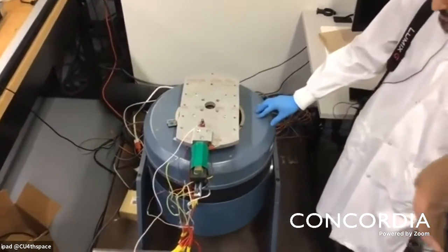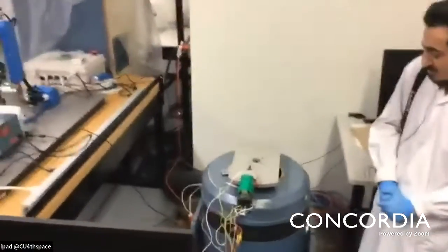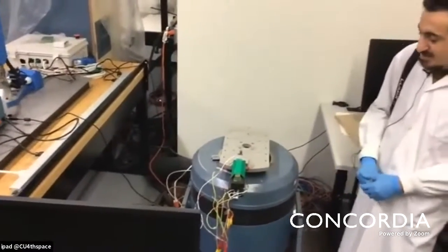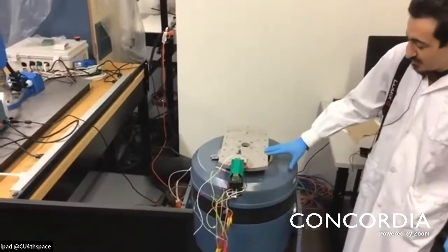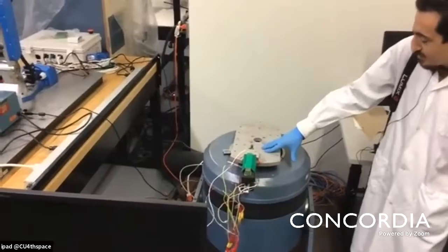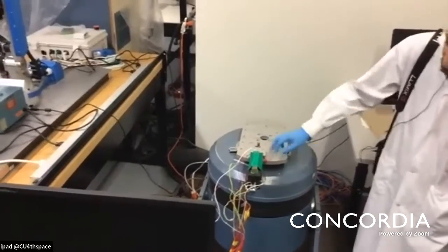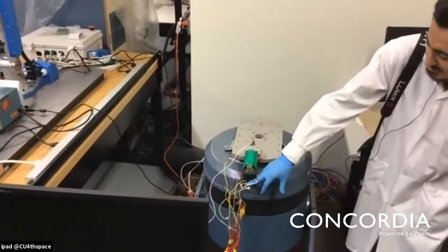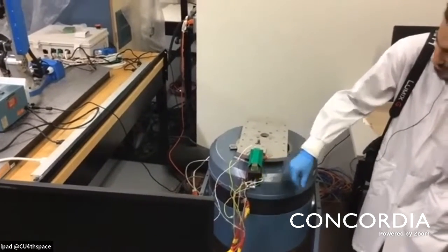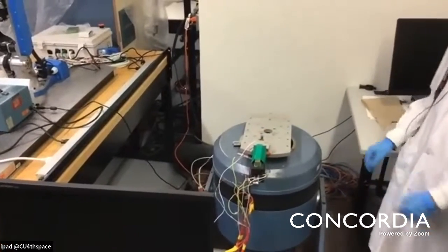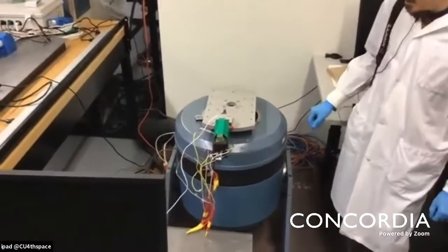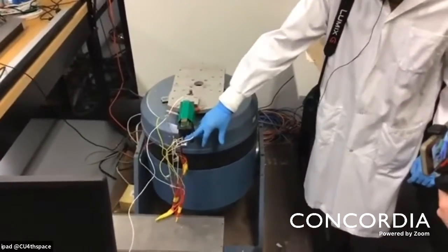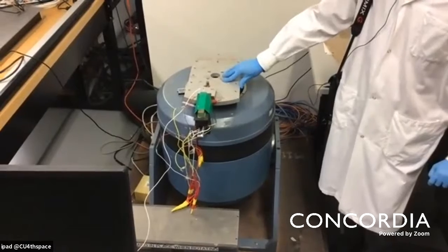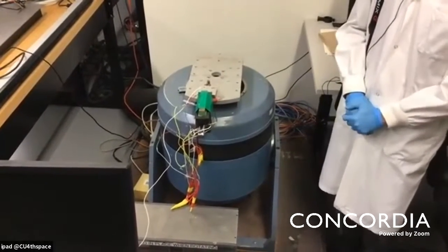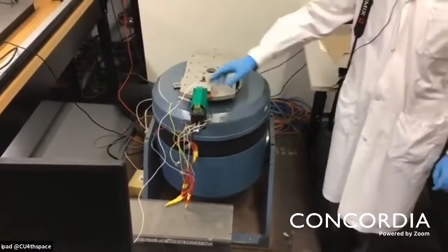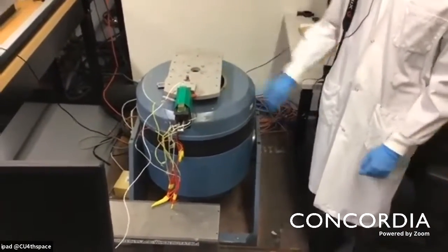So by using this device, we can create several excitation modes with different frequency, different amplitude, and see the response of the structure. Here it is a kind of accelerometer that we installed on the base. Also, we will install a second accelerometer on the structure to see the different response than this accelerometer. The term here is transmissibility. It means the response of this structure relative to the base, and if it is lower than 1, it means that this MRE worked and helped us to suppress the vibration.